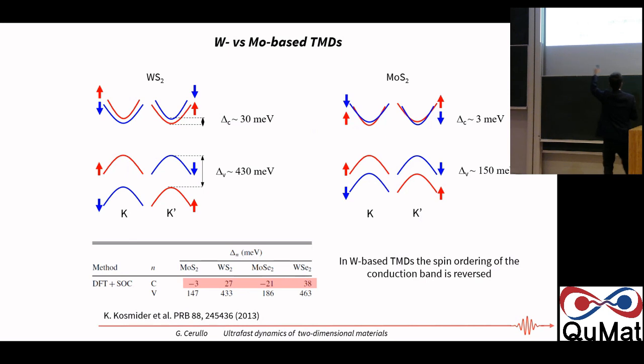a clear difference. For example, in MoS2, if you pump the A exciton, so you start here, you have to conserve the spin. So you go here, and now the opposite spin has higher energy. But here in WS2, you pump the bright exciton, you go here, but the opposite spin has lower energy. So the spin ordering in the conduction band is reversed.